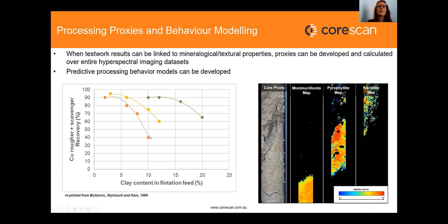This is real data. There's three different ore types here in different colors. And you can see that as the clay content increases in the flotation feed, we get a dramatic decrease in the copper recovery, both in the rougher and scavenger. And so this is a really important trend, really important to know about. So if we think about this principle that there's a relationship between the content of the clay in my feed and how much copper I'm actually going to be able to recover.